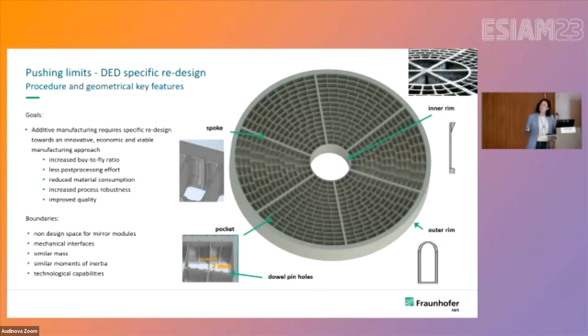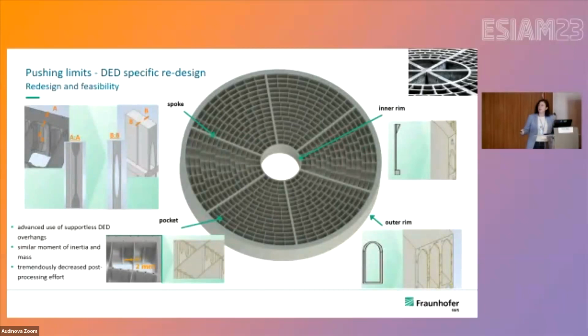Concerning design, we have a couple of issues working quite closely with ESA, because as you can imagine, some of the previous design approaches were not so AM friendly. Therefore, we needed to take critical parts like the spokes, inner rims, outer rims, and pockets, and approach them closely. For instance, we don't have the possibility of having support structures with DED. Therefore, we changed the geometry of these spokes and pinholes to avoid the need of support structures and made them a more DED-friendly structure. You can see it here.